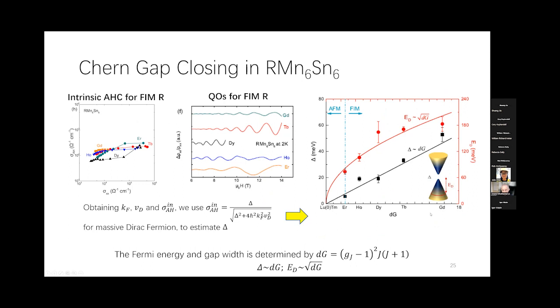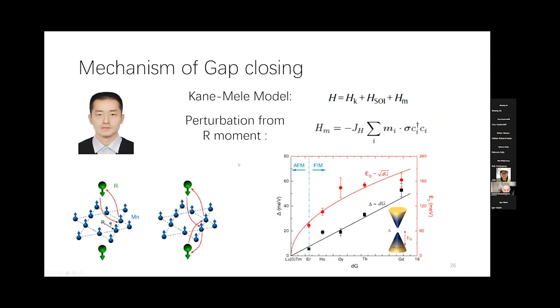So the x-axis is the de Gennes factor of the rare earth, and the y-axis is the gap size and the Fermi energy. We see the delta is dependent on the de Gennes factor, while the Fermi energy of massive Dirac fermions depends on the square root of the de Gennes factor. So this is a very interesting observation. Clearly, we cannot explain it by the Kane-Mele model, because the Kane-Mele model only explains the nearest neighbor hopping between the atoms.